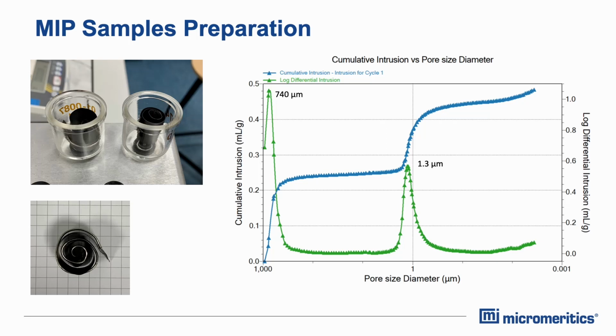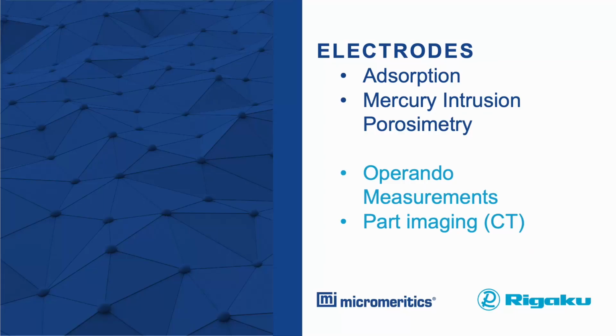So I think a value of around 740 micrometers is reasonable for the filling just in between the electrode and the spiral, and then the real pores that we can expect for this material have their maximum at 1.3 micrometers. With these examples, I now hand back over to Stephan.